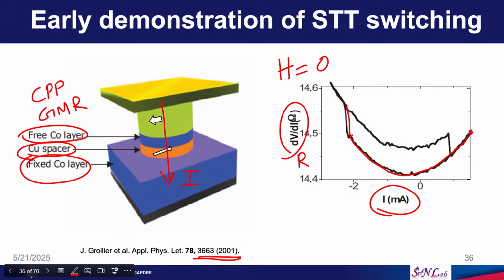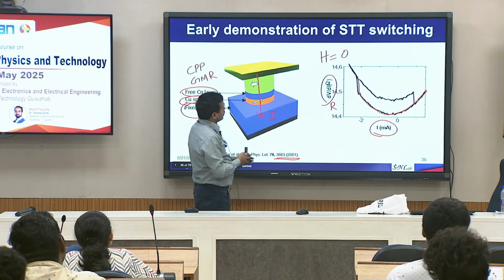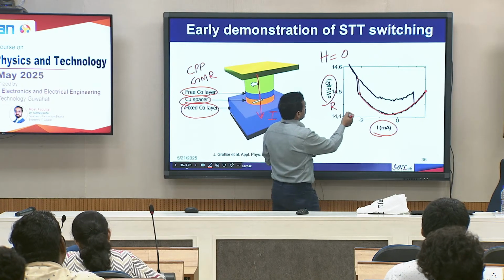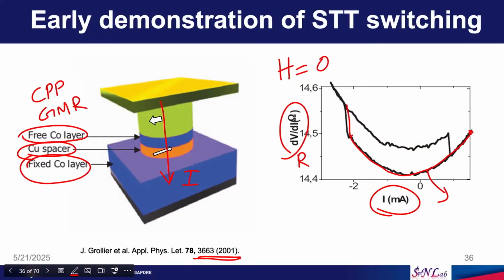Then suddenly you see a change in the resistance. Okay, that is because the current in this particular direction has changed them from parallel state to anti-parallel state. So, we have low resistance when the magnetizations are parallel, right. We have high resistance when the magnetizations are anti-parallel. Okay, so, they noticed that at certain value of current, this device switches from parallel to anti-parallel. So, now you have high resistance, because now they are in the anti-parallel state.